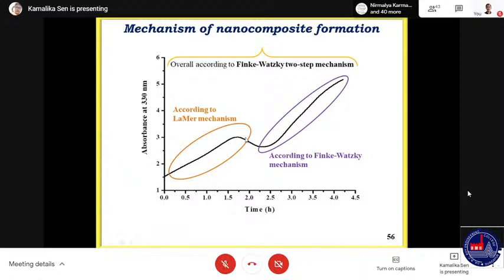The previous one for the palladium quantum dots was autocatalytic growth. One nanoparticle catalyzed the formation of other nanoparticle on its surface, but here the formed nanoparticles, they individually come closer together and aggregate. So this kind of peak falls sharply. Once it starts falling, after some time, then starts the autocatalytic growth. This means here this part starts the Finke-Watzky mechanism. So on seeing the absorbance versus time plot, you can simply deduce what kind of mechanism is going on inside your solution.